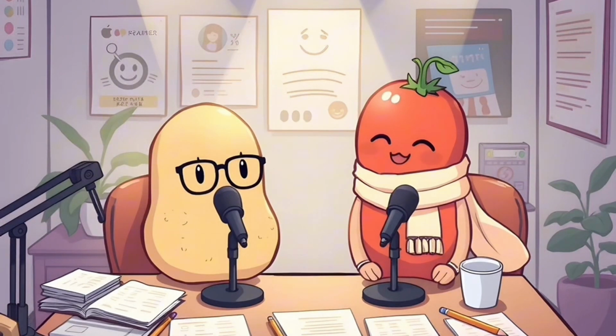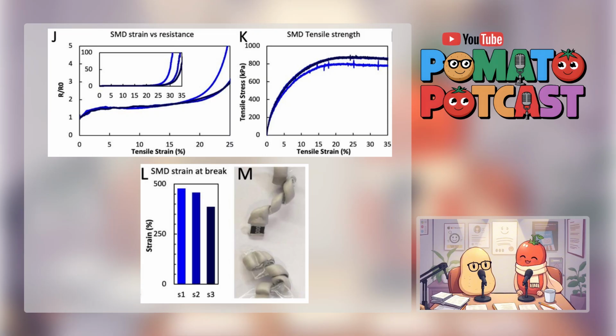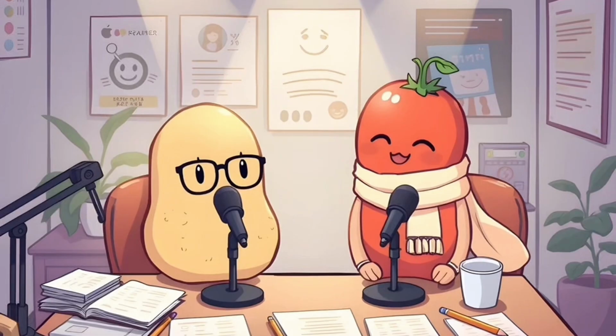And what about those soft solder joints holding the chips? Are they the weak point? They tested that too with resistors integrated. Those joints also showed similar strain tolerance, failing electrically around 31% stretch. And interestingly, if they did fail mechanically under extreme stretch, the break usually happened right at the interface between the ink and the component body. It didn't tend to peel off the underlying flexible film. Right, so the adhesion to the substrate is really strong, okay?